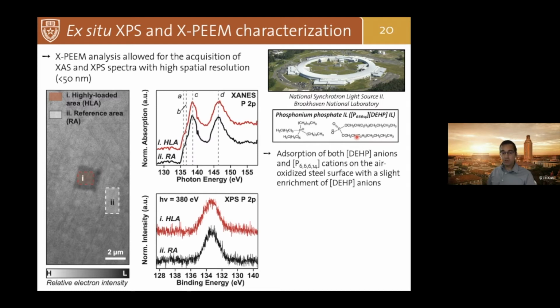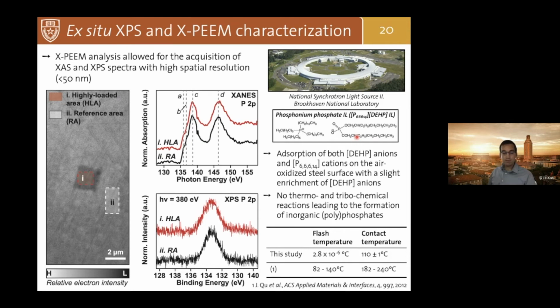So clearly these results show that there is no stress-assisted chemical reaction leading to the formation of a film. The ionic liquid is adsorbed as it is on the surface. So this seems to be in contradiction with what was reported in the literature. But after modeling the temperature during the sliding experiment, we understood that in our case, we have a very minor change in temperature at the contact during sliding, during AFM. So our contact temperature during our experiment is still the bulk temperature.